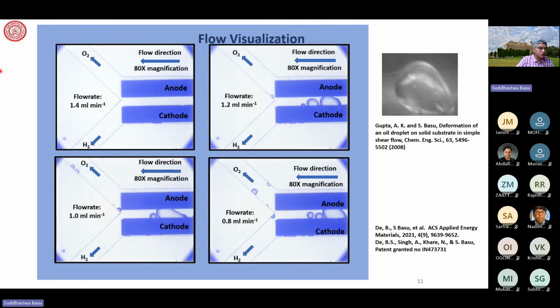So we have proven this because the bubbles become like this, and at the time of detachment, the drag force acting from the outer fluid is exactly equal to the attachment force that is there because of the interfacial tension, and it has been overcome and the bubble detaches. So a bigger bubble will detach at a lower volumetric flow rate or lower velocity, but when the velocity is large, the drag is large, and a small droplet will detach, and as a result no intermixing takes place when you have a high velocity. Whereas at the low velocity of 0.8 ml per minute, you can see that it is growing bigger and bigger, the shear rate is not very high, and then intermixing possibilities arise.